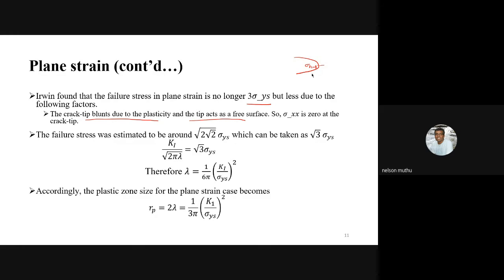Okay, so because of this crack tip blunting due to the plasticity, sigma_xx goes to 0, and therefore using the Tresca criterion, the stress that is required to initiate the yielding is much smaller than what we had used in the previous derivation. So it was found out that the failure stress was estimated to be around square root 2 root 2 sigma_ys. How we got that, we will not look into. But for a moment, just take it for granted that this is the value at which the material yields.